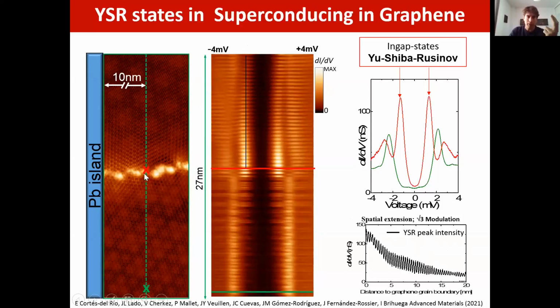Second, the magnetic moment and the superconducting properties are borrowed from the lead island, which is here. So this is a Yu-Shiba-Rusinov state in a proximitized superconductor. And third and fourth, it extends very far away. 20 nanometers is a huge extension for a Yu-Shiba-Rusinov state, and it's atomically modulated with this root-3 periodicity. So, a very peculiar Yu-Shiba-Rusinov state.